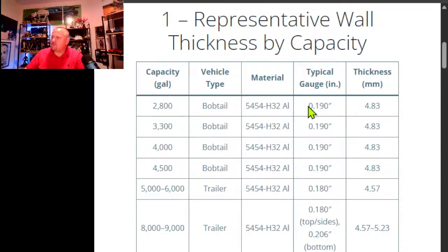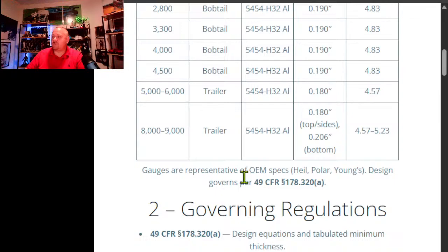For 2,800 gallons, the typical gauge is 4.83 millimeters. This is the typical, representative. 3,300, 4.83. 4,000 gallons, bobtail, 4.83. 4.83 for 4,500 gallon. Then when you get into the 5,000 to 6,000 gallon tankers, they are 4.57 millimeters thick. And then when you come up to 8,000 to 9,000 gallons, these are 4.57 to 5.23.